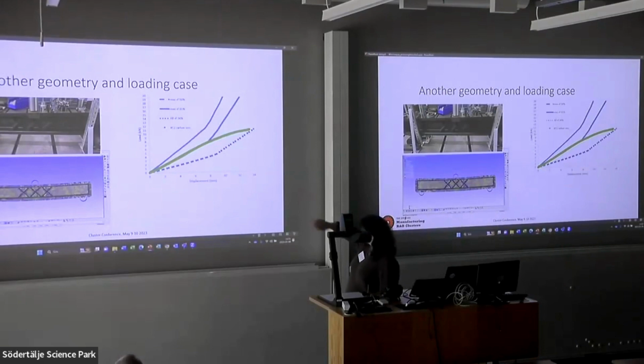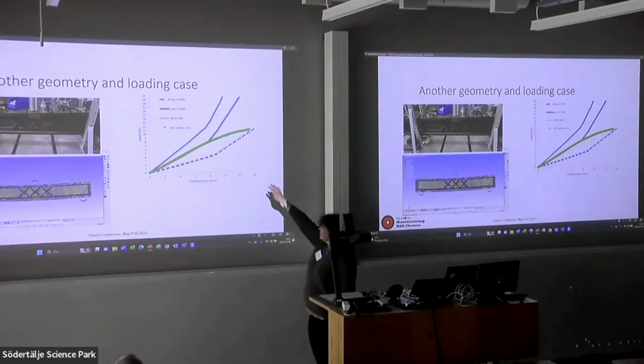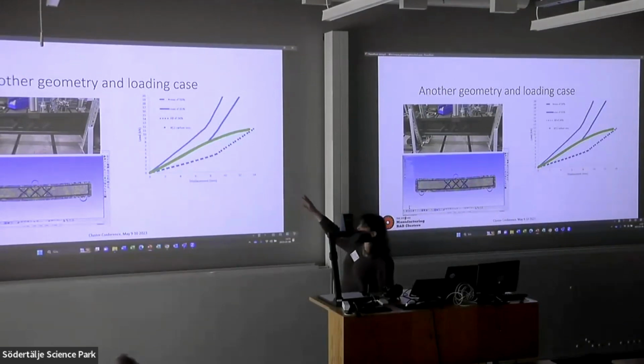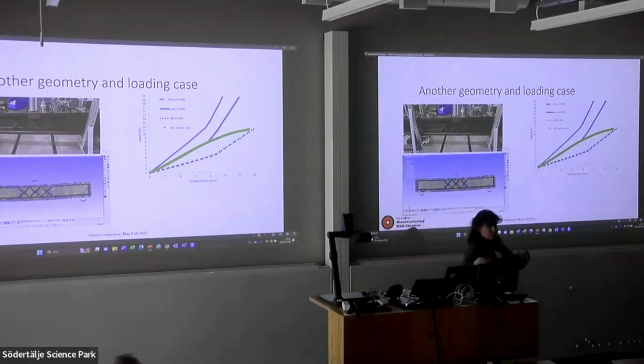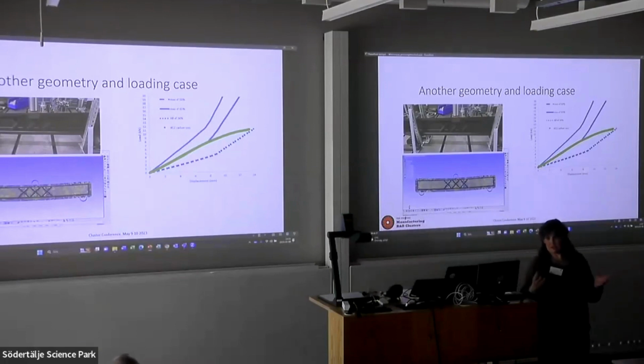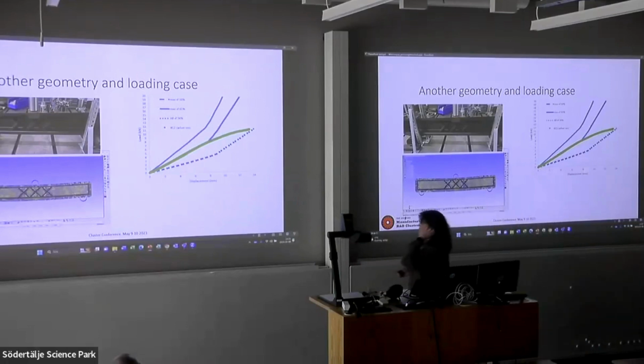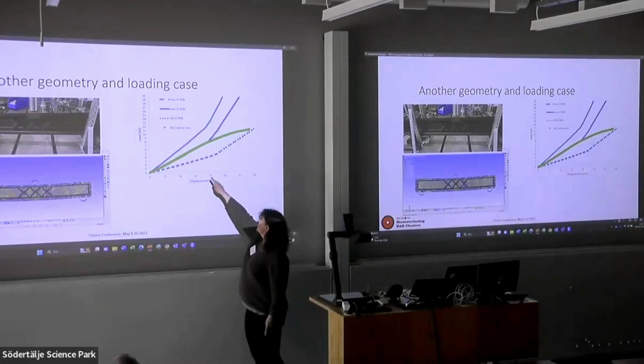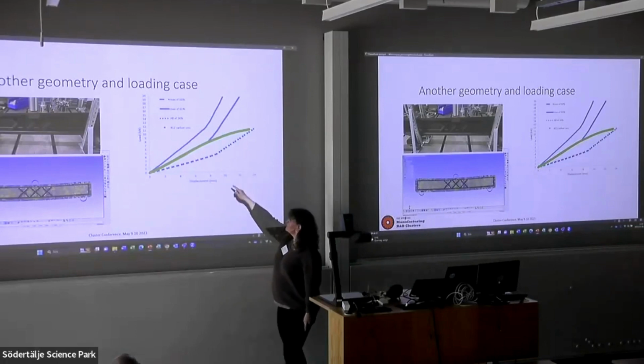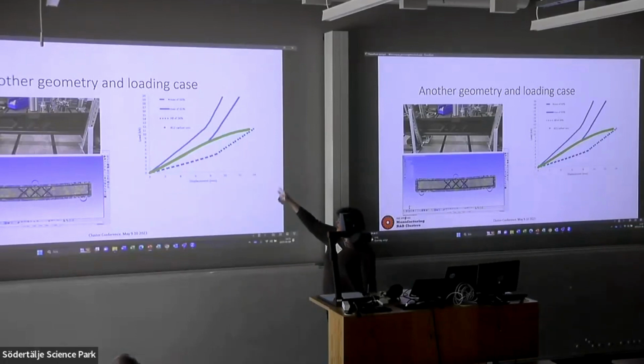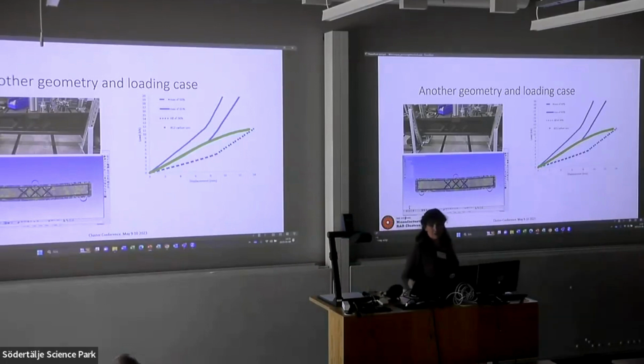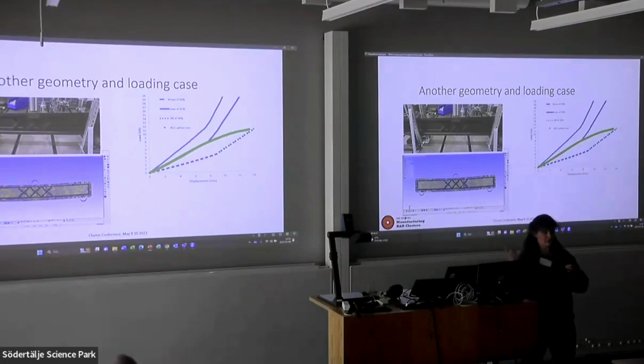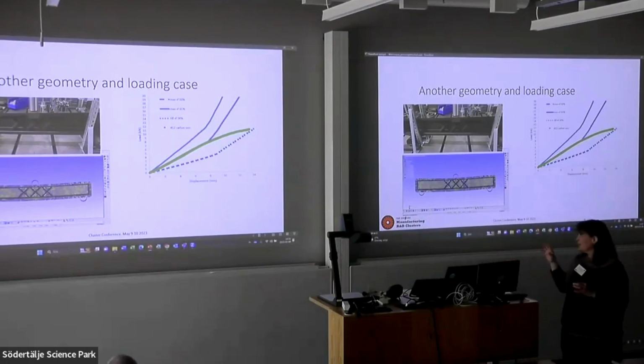But then I changed it. The first one was with allowing the fibers to move quite a lot, allowing up to a 65% volume fraction. That gave the line that was too high here. The green line is the experimental results. 50% was about right. And if we use isotropic data sheet values, then we get a line that's quite a lot lower.